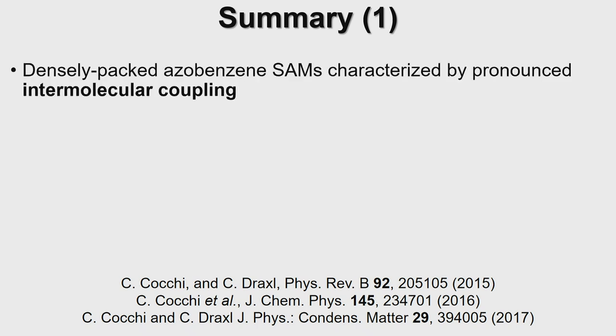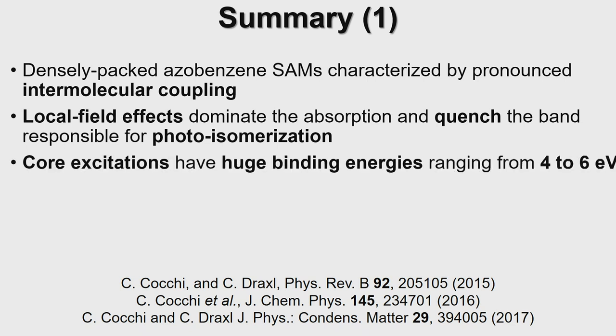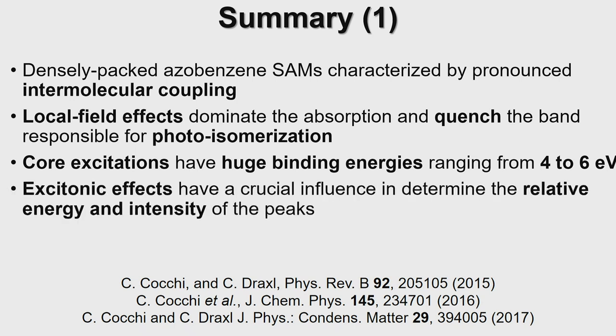To summarize this first part, we have demonstrated that densely packed self-assembled monolayers of azobenzene are characterized by pronounced intermolecular coupling ruled by local field effects that dominate the absorption by quenching the band responsible for photoisomerization. Core excitations have huge binding energies, very large, ranging from 4 to 6 electron volts. Excitonic effects have crucial influence to determine the relative energy and intensity of the peaks. This was all confirmed by very good agreement with experiment.